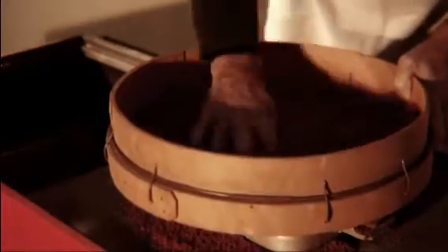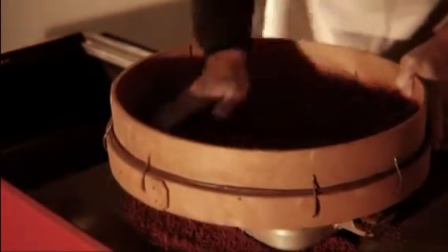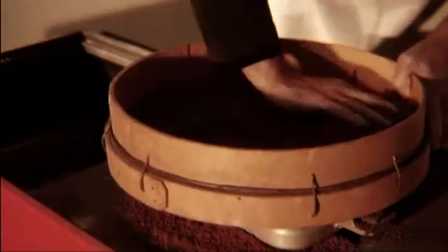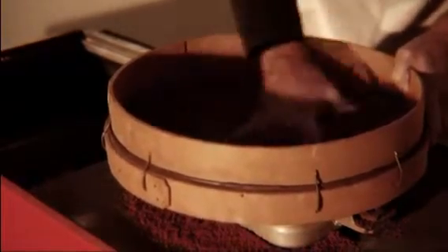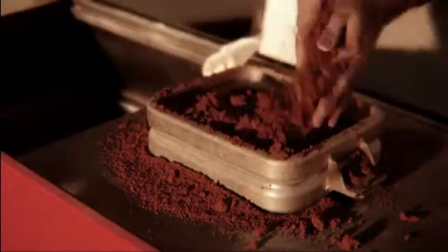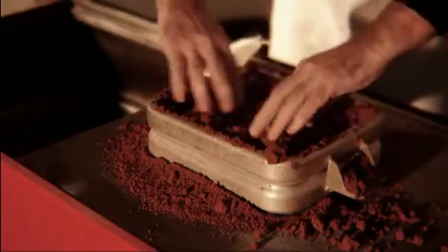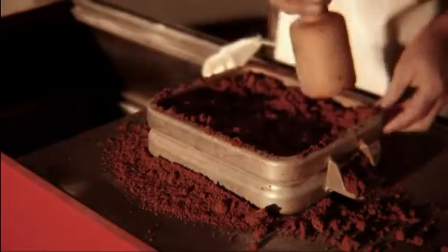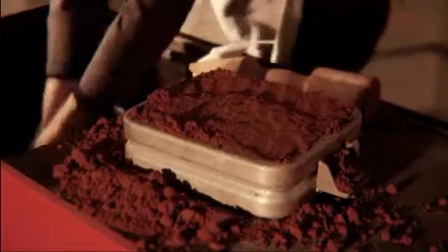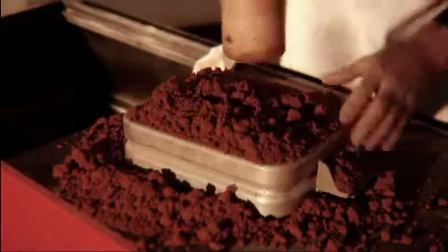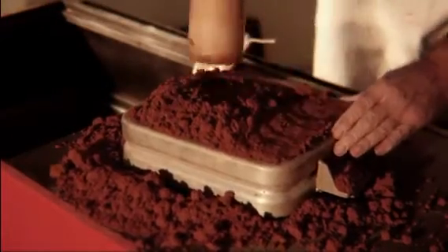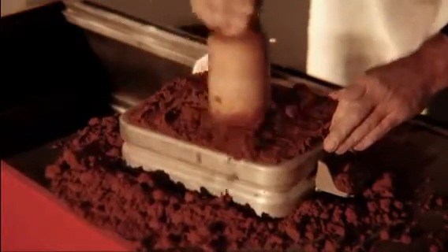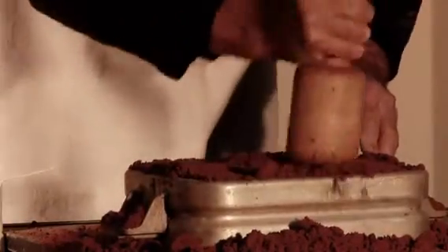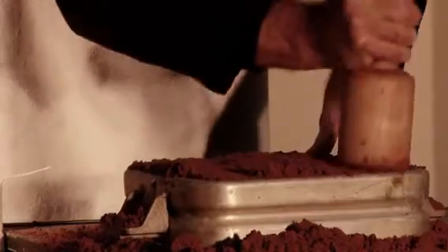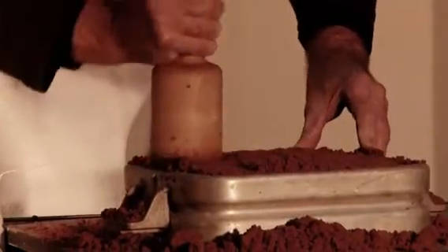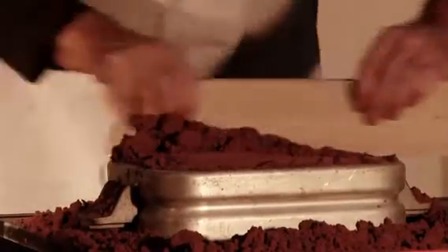The drag is filled with moulding sand, which is rammed to make it firm. Staff, make sure that the sand is rammed into all the edges and corners, as the mould could collapse if there are any gaps. Oil-based sand should be used. If water-based sand is used, it should not be too wet, as the molten metal will cause the water to turn to steam and the mould to explode and the molten metal to run free. Staff, check risk assessments and control measures to establish the correct moisture content of the sand.